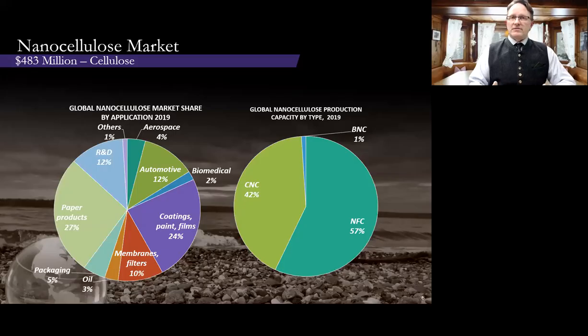Now, nanofibers have a lot of uses and applications. They can be used in composites, barrier applications, for example, such as packaging and membranes and films, used as a rheology modifier, so coatings and paints, or in transport functions for biomedical. Now, if you look at the breakdown between those two types of nanofibers, you can see that nanofibrillated cellulose is about 57% of the market. Crystalline nanocellulose, or CNCs, are 42%. Then we have this little sliver up here, and that is bacterial-based nanofibers.